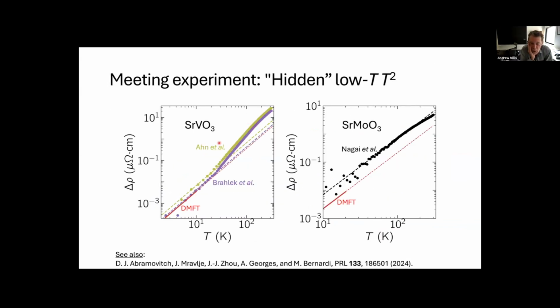So for the strontium molybdate, I wanted to ask: we see that the delta rho, which I assume is the resistance measured relative to some low T value, has a slope which is parallel to your DMFT curve, so that the resistivity is T squared within the admittedly large scatter at low temperatures, right? So does the offset mean that there is some kind of discrepancy with the coefficient?